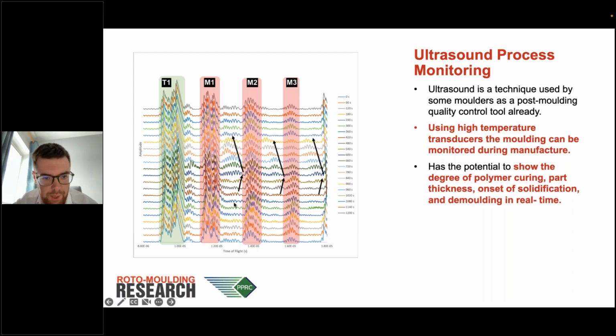And what you can see is that during the cycles, so at time 0, and then the gray line up here is at the end of the cycle, there is a peak that appears during the heating cycle, and then it slowly shifts back to the left during the cooling cycle. And it would appear that that is the polymer thickness itself, and you could measure between these peaks and work out what that thickness is.